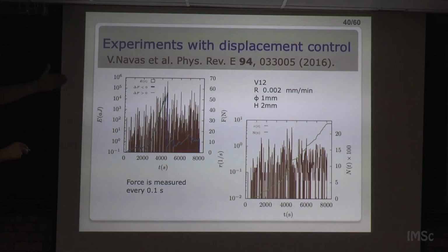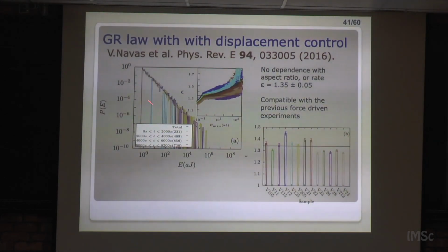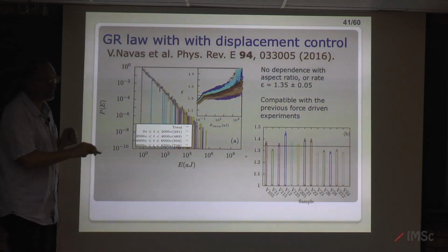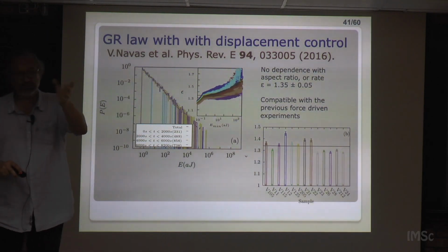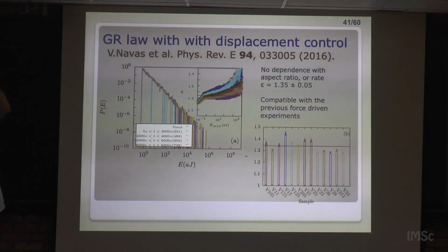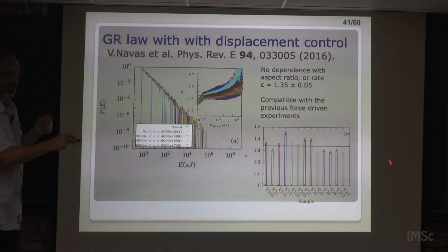Well, in this work, we also tried to compare the energy of the big events with the force drops. You can go there. The correlation exists, but it's not very big. But we also checked that it's stationary in this case. And the exponent, here are different samples. Here what we tested is the aspect ratio, because I know for the people that work in fracture, the aspect ratio is very important. The data you have here is not ordered by aspect ratio.